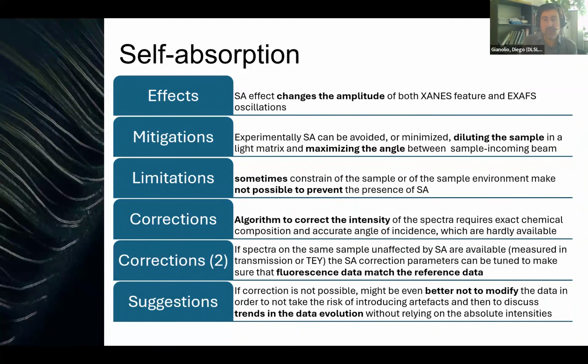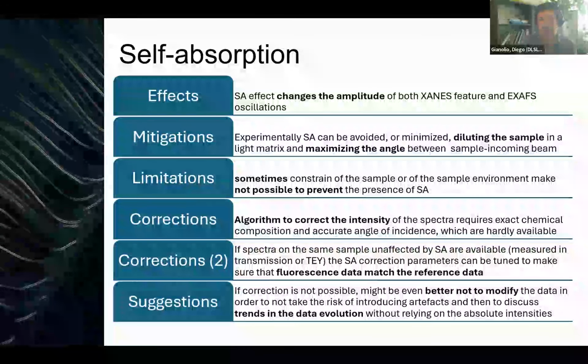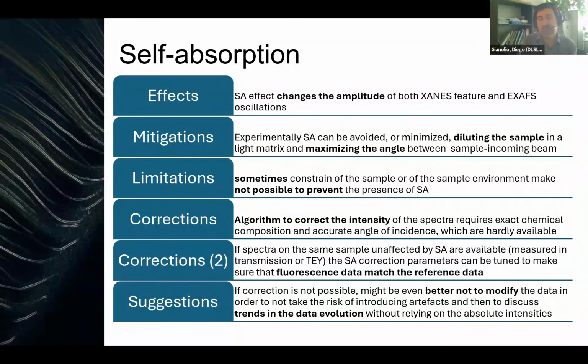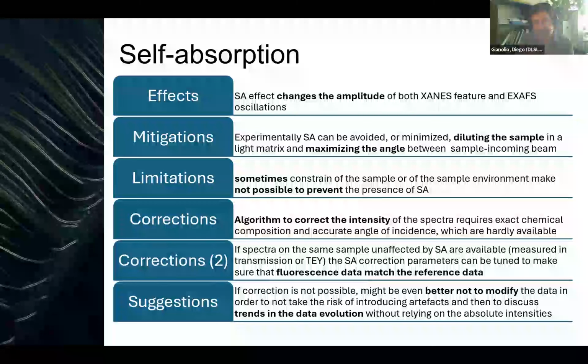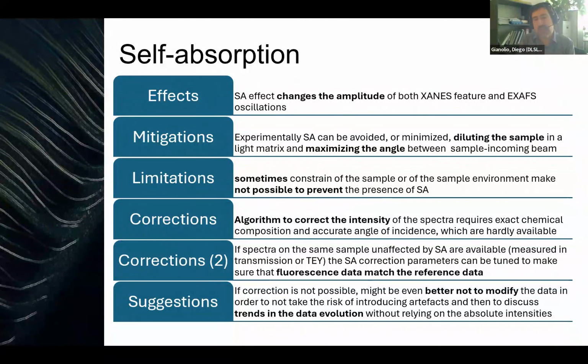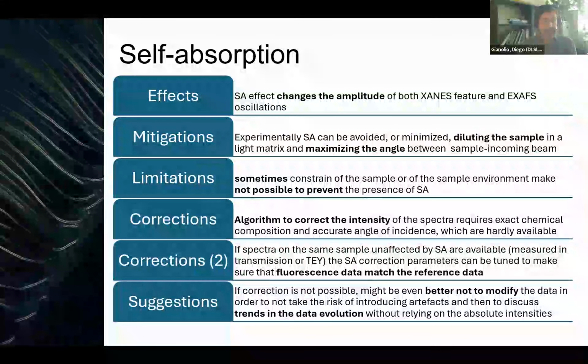And if this is done for one reference material that has a well-known composition, you can also then reapply the same correction parameters to other samples. Of course, taking into account that the sample preparation might be slightly different.